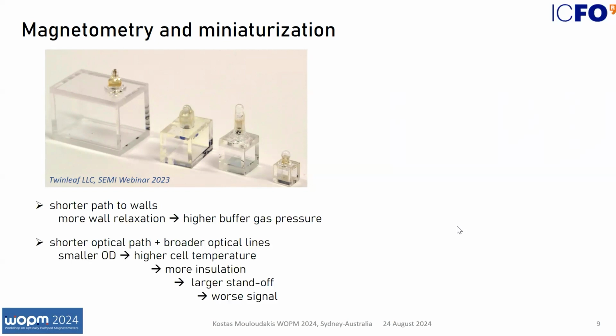But also, miniaturizing means that we have shorter optical path length for the laser beam. And the fact that we have also high buffer gas pressure in the cell broadens our optical lines, and these together lead to smaller optical depth, meaning lower magnetic signal. And to compensate for that, we need to increase the cell temperature to increase the optical depth, but this has more challenges. We need more insulation. This leads to larger standoff distance, and of course, worsens our signal.